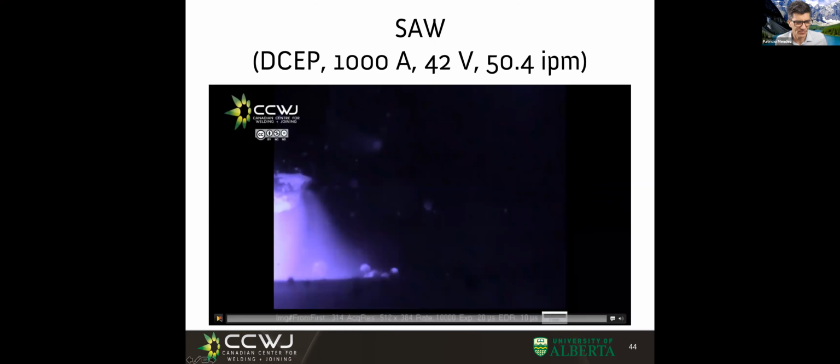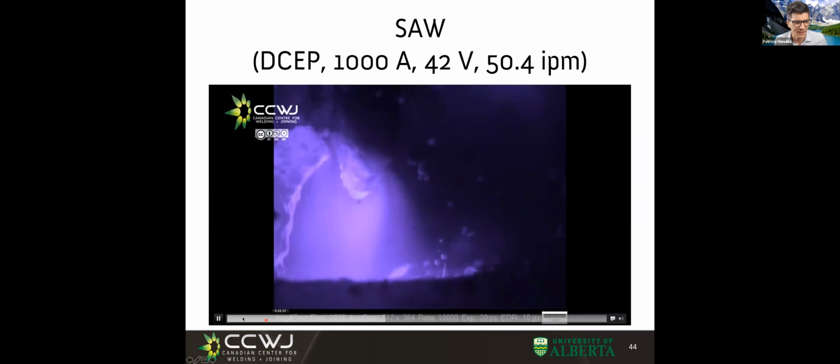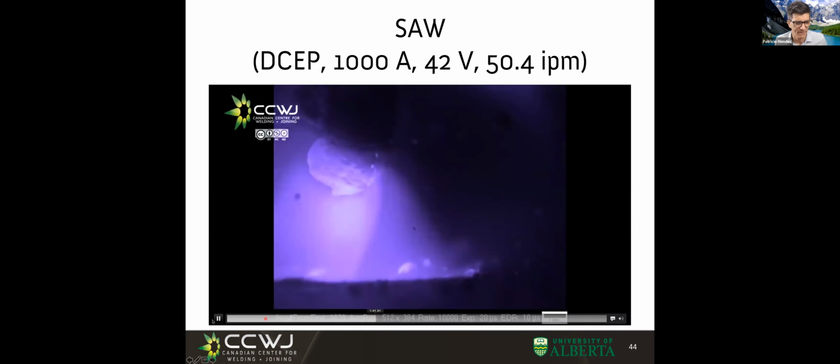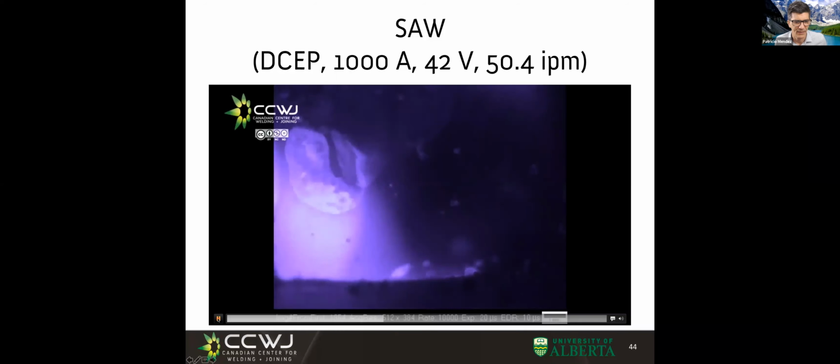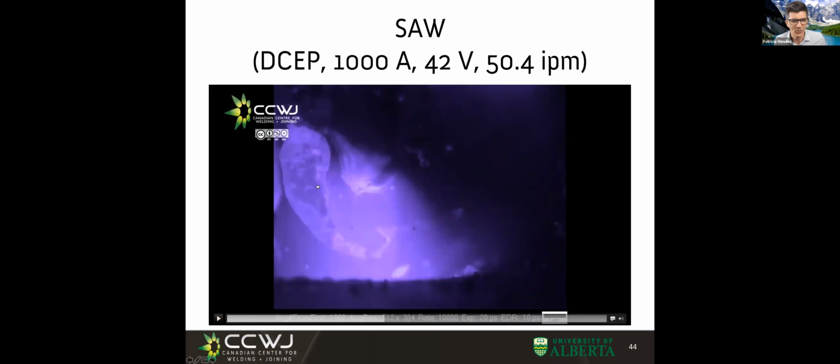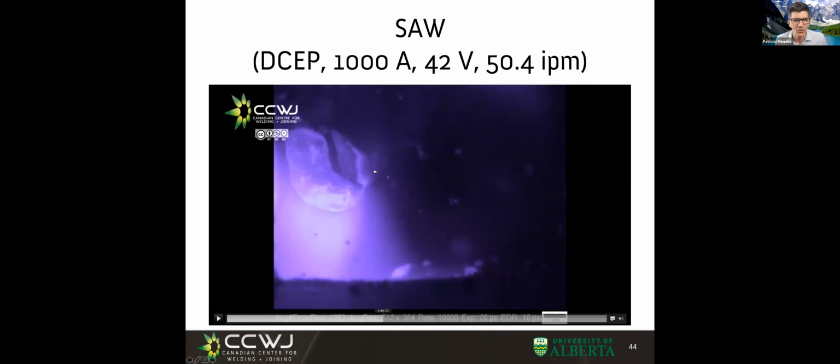But we have photos and we have published those in the papers. Okay, well, more or less, you get to see how this went to the right, and this other part that broke was having some sort of... there you go. You see how it's making a turn. And this is an electromagnetic instability. This has nothing to do with rotating transfer. And this had never been observed, except in our lab.